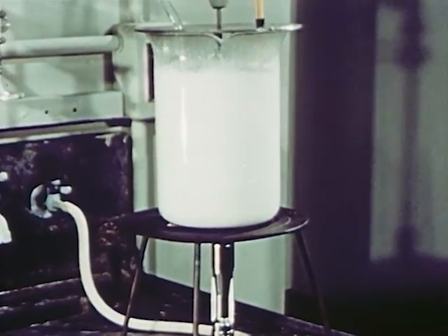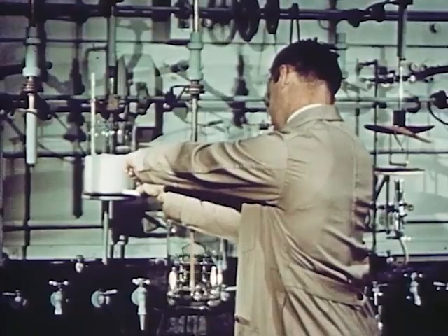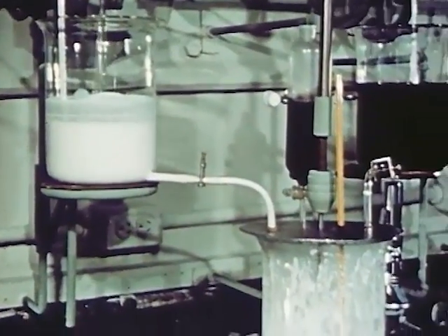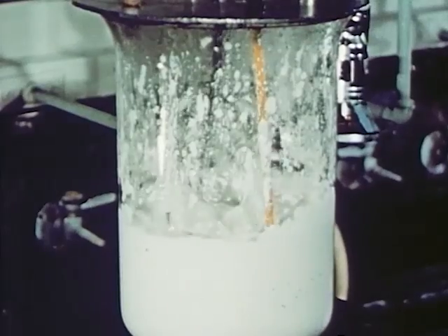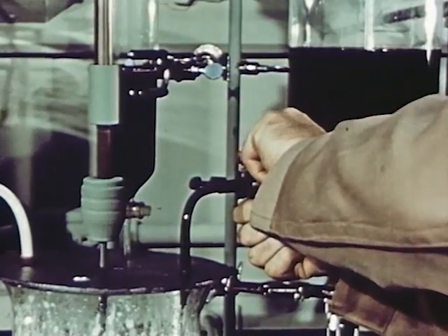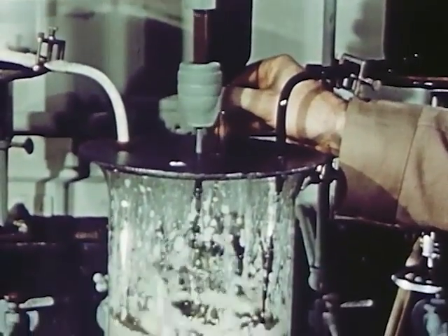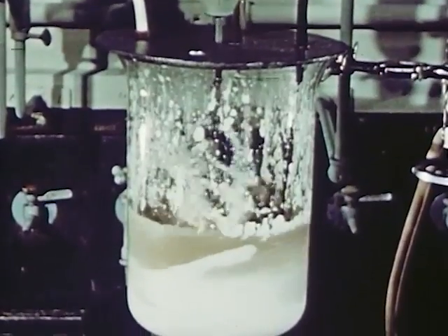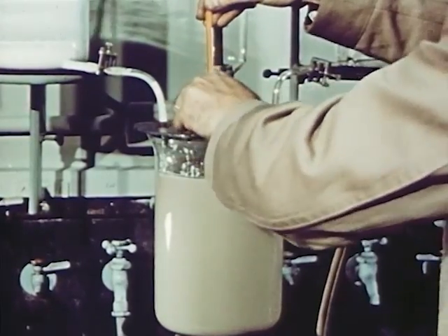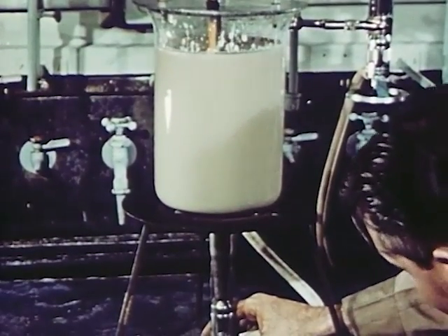It is at this precipitation stage that the making of composite pigments differs essentially from pure titanium dioxide in that precipitation takes place in the presence of calcium sulfate, formed by the addition of a water slurry of the highest grade of limestone to sulfuric acid. The calcium sulfate produced is of the proper particle size, purity, and surface, because the strictest controls are kept upon such crucial factors as dilution, rates of flow, temperature, and acid concentration. The titanium solution is added to this calcium sulfate along with nuclei just before hydrolysis, so that the titanium hydrate precipitates and is deposited upon the calcium sulfate, forming a tight union of these substances, a truly coalesced composite pigment.